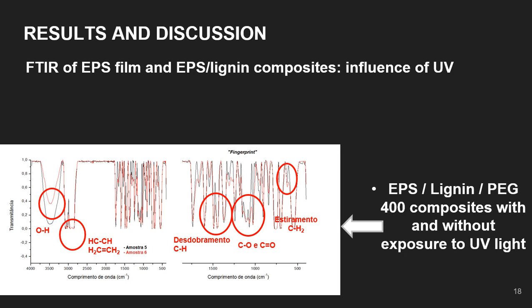In relation to the other bands, an increase is observed both in relation to the carbon-carbon, carbon-oxygen, and carbonyl connections at 1,200 cm, and in the CH2 stretches, which may indicate an increase in vibrational energy in the main chain.